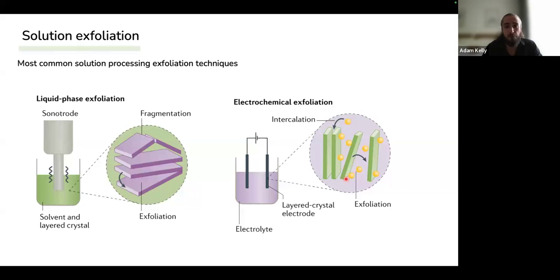So the two most common solution processing techniques are known as liquid phase exfoliation, where we apply sonic energy into a solvent with a crystal in it, and this will then fragment and exfoliate our material. And then another way to do it is with electrochemical exfoliation, where we intercalate ions in between the layers of the bulk crystal, which then facilitates delamination.